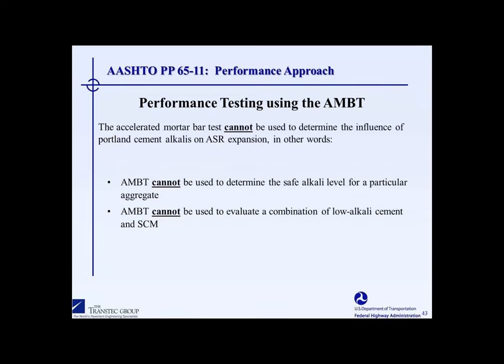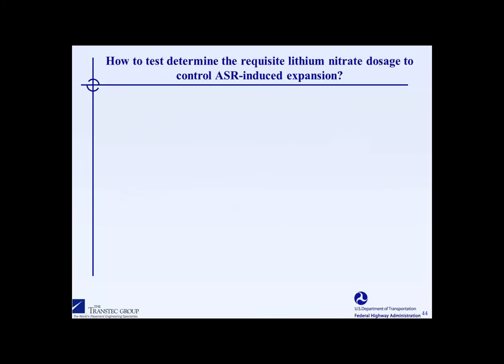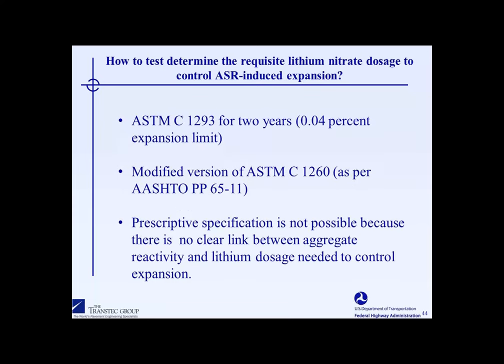And just a couple other points here. You cannot use the mortar bar test to determine an alkali threshold, nor can you look at the effects of low alkali cement, again because the host solution is providing an infinite amount of alkalis, and it would dwarf any effect of the contribution of alkalis coming from the individual materials. Now, lithium nitrate is a viable material that, when used in sufficient dosage, can suppress alkali silica reaction. Our recommendation with our AASHTO recommended practice is that we prefer and recommend the concrete prism test, but again, you would have to run that test for 2 years.